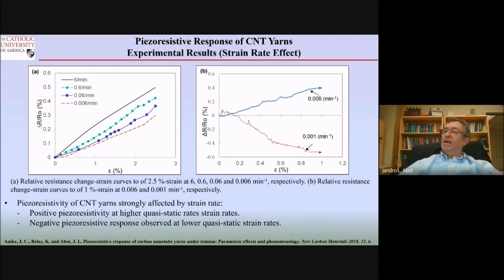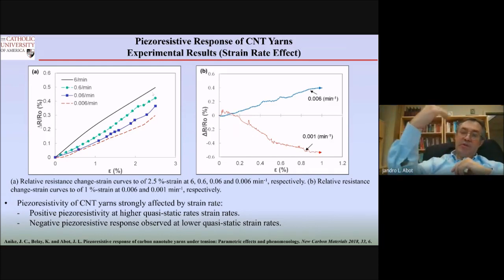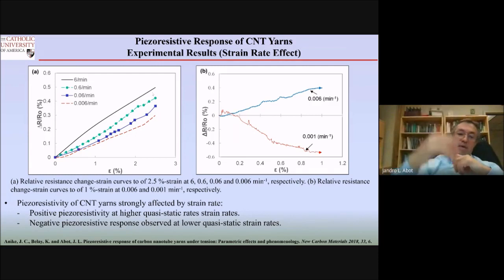And then he says, Professor Abot, I'm really getting these positive responses in the fiber. And I said, well, what's happening? Then we realized that the speed at which we apply the load plays a role. If you see the figure on the left, once you increase the strain rate, the response even increases. This is not unusual in polymers.